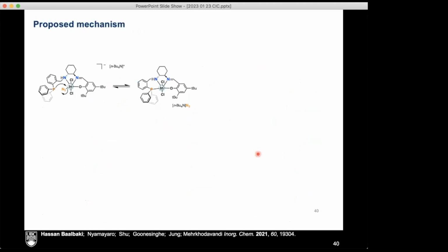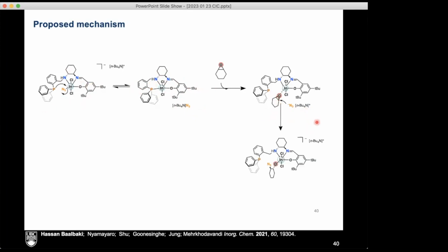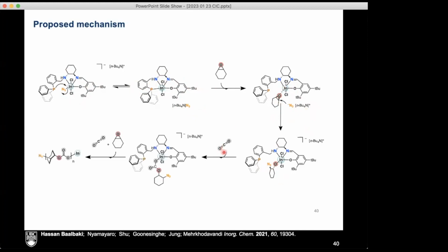in general, then, the mechanism we believe is that the very first step involves the dissociation of the coordinated phosphine, attack of the azide, and this then generates a mixture of different either external azide or internal azide, because they mixed the azide and the chlorides. Epoxide will coordinate. There's an attack, either inter- or intramolecular, on the coordinated azide. There's a ring opening event. CO2 will coordinate.